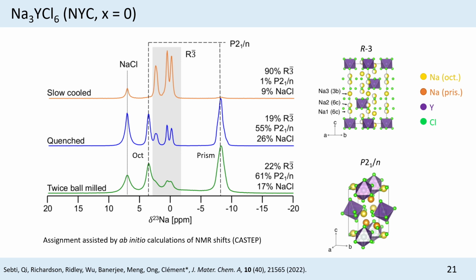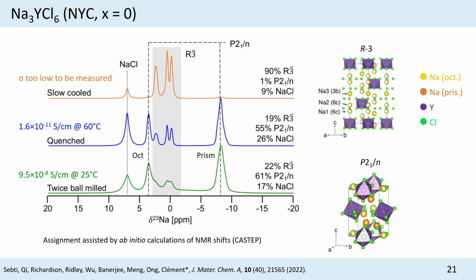Now, if we quench or we ball mill, we start to see the second polymorph of NYC appearing. We also have broadening of the peaks corresponding to the R-bar-3 phase, suggesting again that we have more disorder in the material. Again, when it comes to conductivity, we have a drastic increase going from the slow-cooled to the quenched to the twice-ball-milled sample. Still, this is not great conductivity overall, but clearly we are able to modulate it by changing the processing conditions. Unfortunately, we weren't able to do variable temperature NMR on these samples because they evolved very quickly with temperature. So clearly they are not very stable.